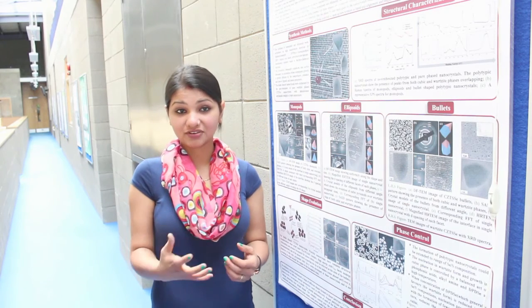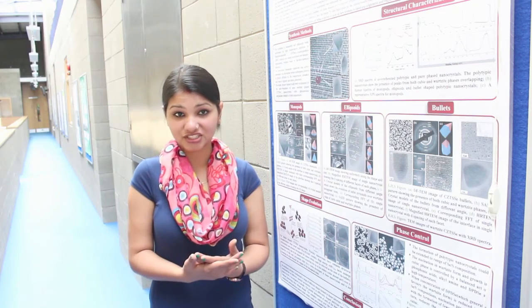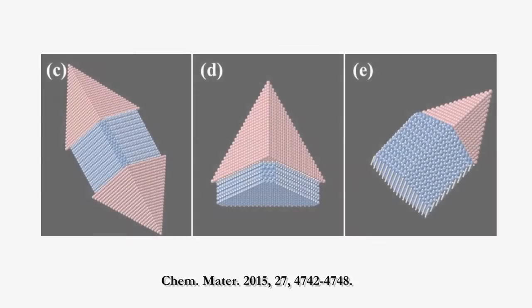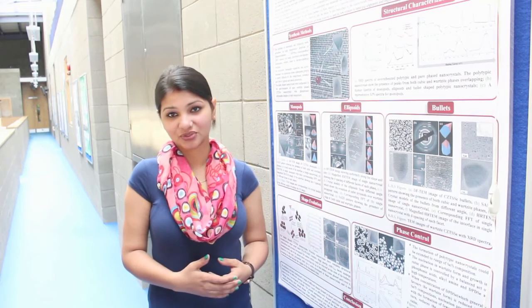By carefully selecting the ligands and the metal precursors which are compatible with each other, and also the temperature windows for nucleation and growth, the shape, size, phase ratios, and monodispersity could be very nicely controlled in polytypic nanocrystals. The wide range of control parameters and complex chemistry makes polytypes interesting and at the same time very challenging structures in colloidal nanocrystal chemistry.